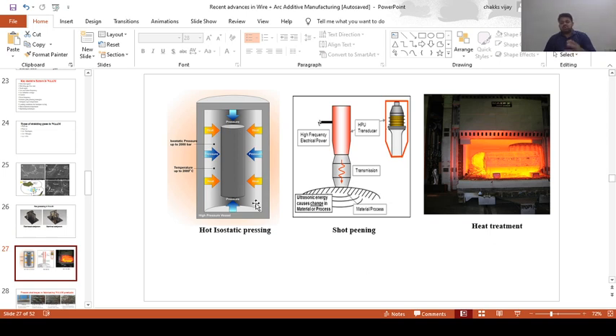Okay, then the other most important thing is shot peening. In this shot peening technique, an ultrasonic transducer will be hitting the workpiece, which is nothing but a hammering effect. Obviously, due to the shot peening effect, a lot of the open porosities get closed. So automatically a lot of compressive residual stresses build up in the component, which is more favorable for tribological applications and even for corrosion resistant applications as well.